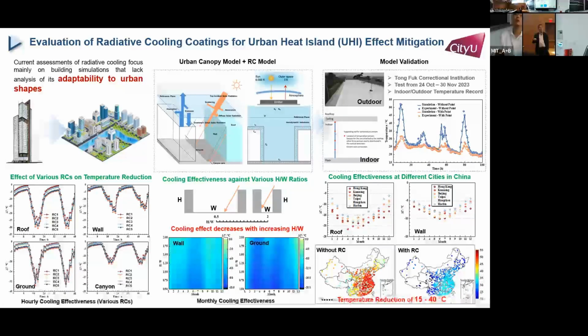If two buildings are nearby, some of the sunlight will be blocked by the nearby building. If we use radiative cooling, the effect will not be that significant. So if we have a higher height-to-width ratio, the cooling effect will actually be reduced. We have also applied the model across China, in different cities, and found that if the cities in eastern China utilize spectral radiative cooling, the city's temperature can be reduced by at least 14 to 15 degrees Celsius compared to cities without using spectral radiative cooling.